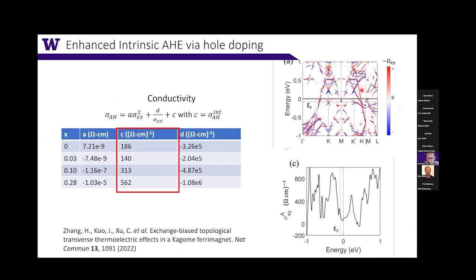Because you have this Berry curvature source everywhere in this compound, there's really nothing special about the Fermi level for the terbium manganese 166. In fact, if you hole dope, which is what we are doing by replacing manganese with chromium and reducing the number of d electrons, then you will get a much larger anomalous Hall conductivity. And this is precisely what we have observed. The anomalous Hall conductivity is increased by almost threefold as we dope to 0.28.